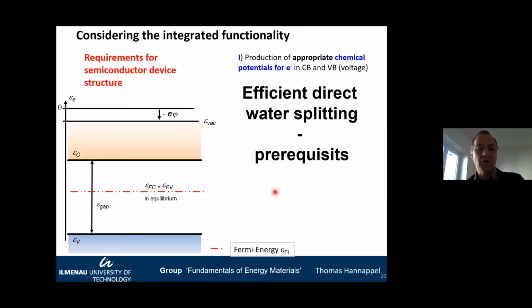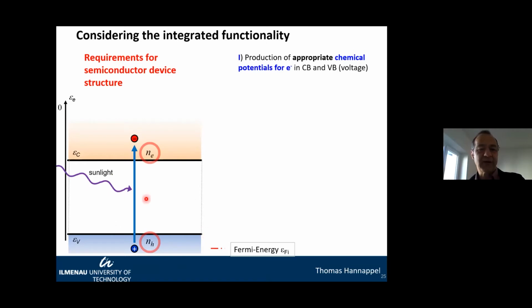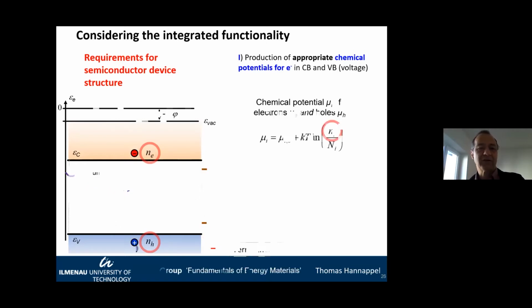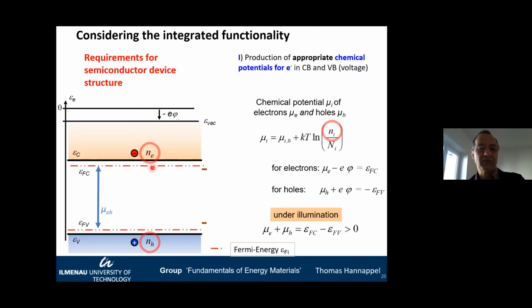In one absorber, normally, and this is very, very important, we have in equilibrium one electrochemical potential, the Fermi level. And after light absorption, after producing an electron hole concentration, we have two different electrochemical potentials. This is the free energy which we can use. This is extremely important to see. This depends on the charge carrier concentrations which we are producing by light absorption.